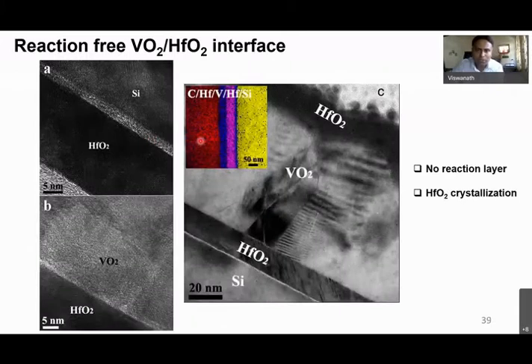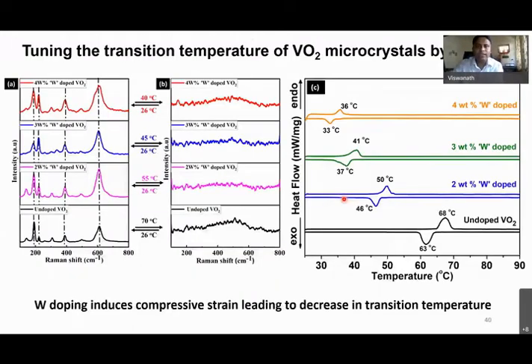Again, I now have to make sure there is no chemical effect. We have looked carefully at the TEM cross section. There is no reaction layer. There is some evidence of Moiré fringes, which might indicate there is a compression, but of course we have not quantified. And the second method is the doping method, already established in the literature.